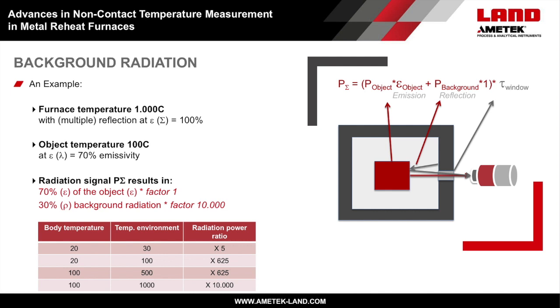Let's take a look at a short example. If an object in a furnace has a temperature of 100 degrees C and the furnace refractory has 1000 degrees C, and the object emissivity is 70%, a pyrometer or a thermometer would measure the complete radiation signal of the object radiation power multiplied by the object emissivity, plus the refractory background radiation power multiplied by the reflection of 30% of the object surface, multiplied by factor 10,000 because of the higher background temperature.